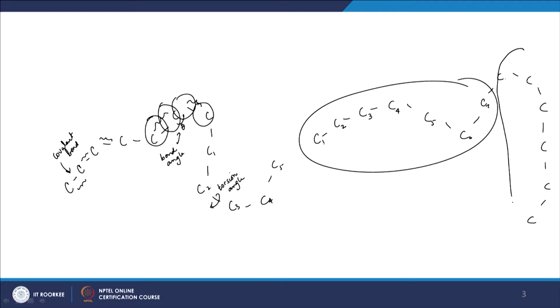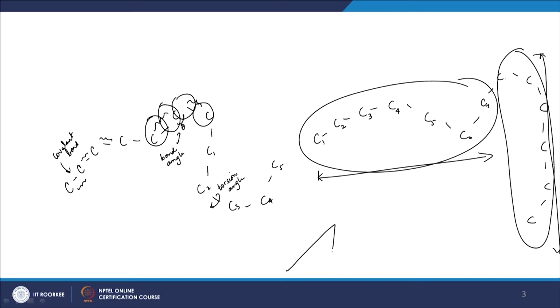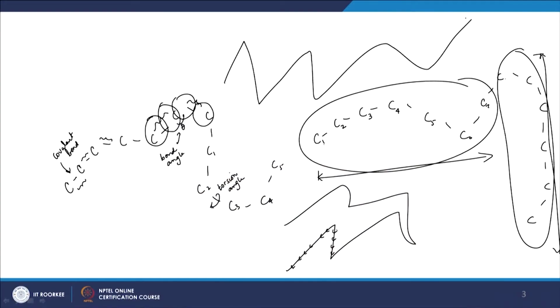Okay. So what I then do is, I will take this entire distance and this entire distance and refer to that as segments of my model, such that I will build my polymer model as composed of this kind of segments, where each of these segments can really move in an uncorrelated fashion, because this will correspond to a certain number of carbons, of course, and this corresponds to a certain number of carbons, but after this much distance, the carbons have become somewhat uncorrelated, and for this reason I can use a model of a polymer chain that is known as a freely jointed